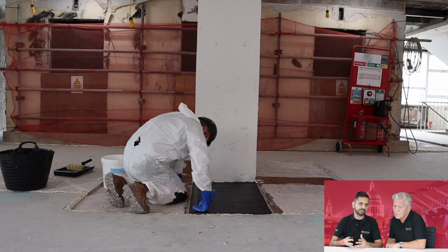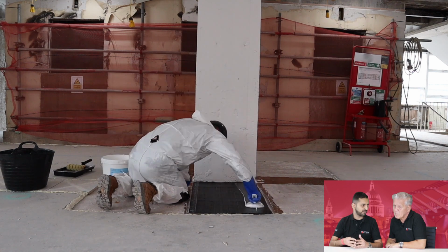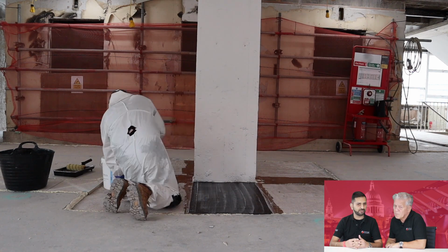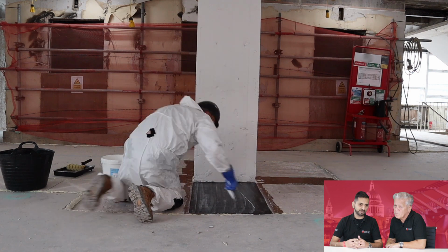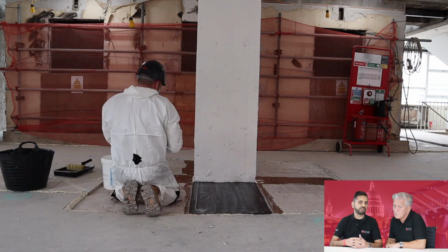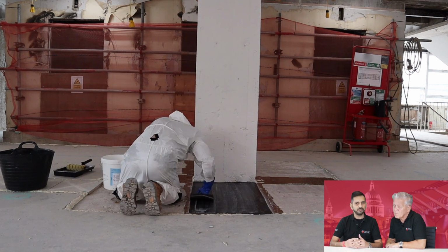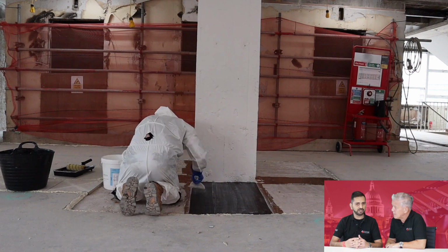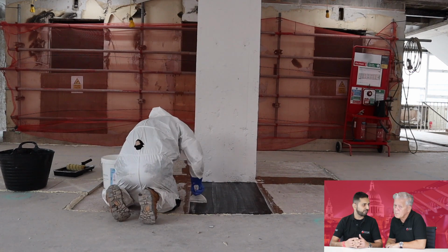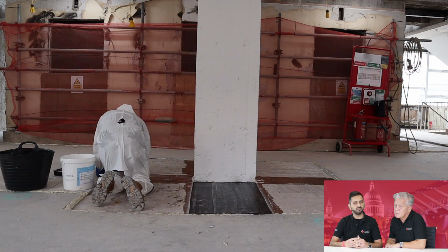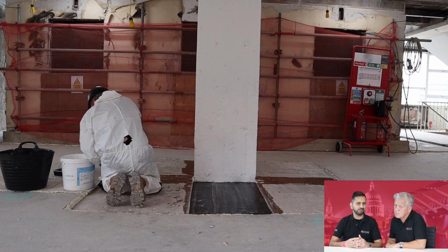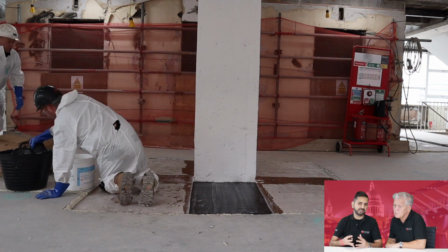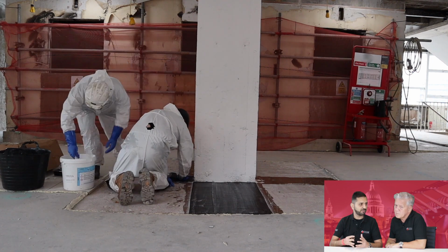We apply the first layer, then another coat of epoxy, then another layer. That's how we build up the number of layers according to the design. Generally, because this was slab strengthening on top of the slab, you're not limited in how many layers you can apply. But if it was a vertical or overhead application, you can only apply 3 layers in one day or one shift. After that, you have to wait for it to initially set, which will be 4 to 6 hours, so you can come back the next day and apply further layers. So that's how the application is done.